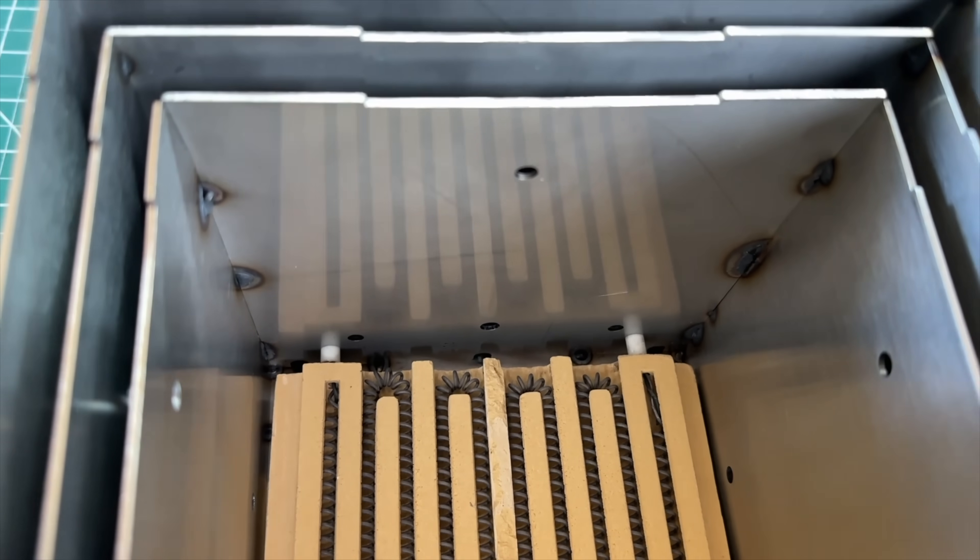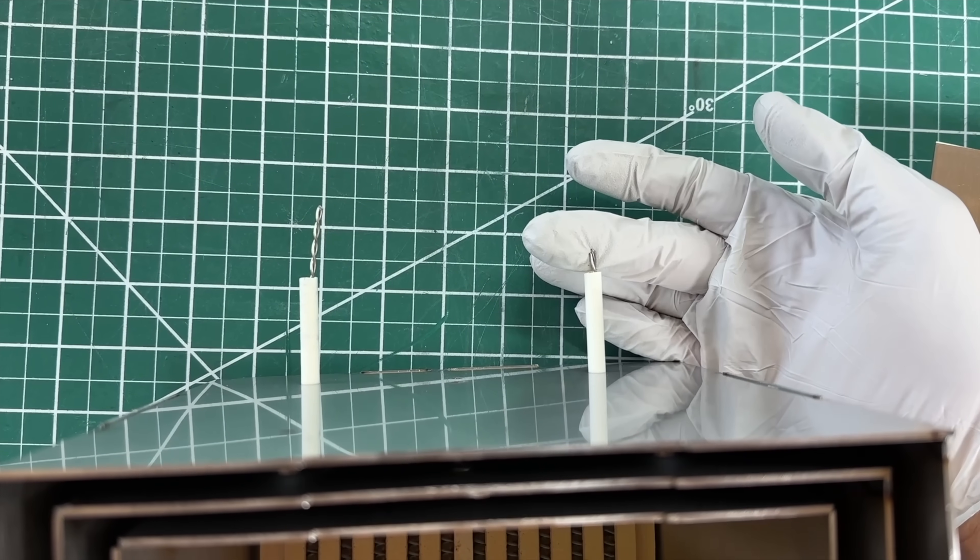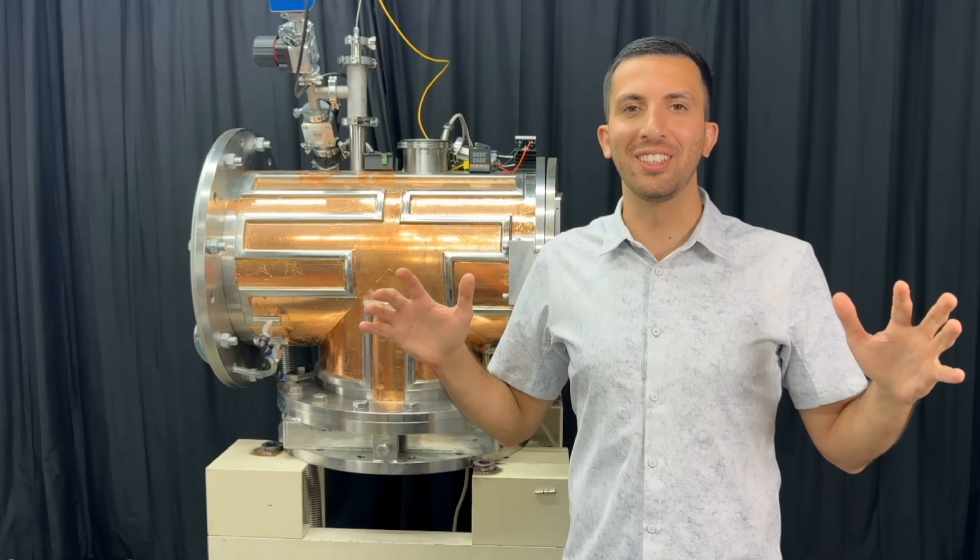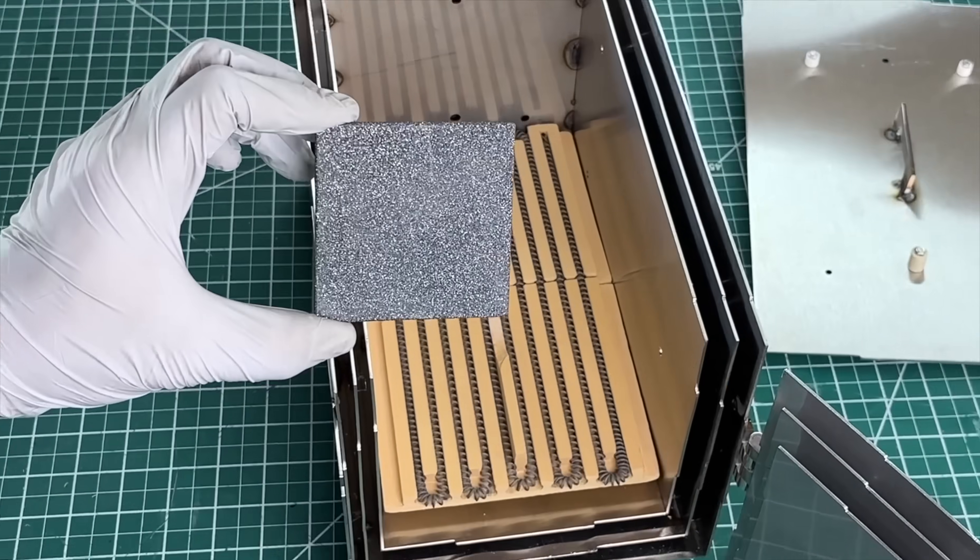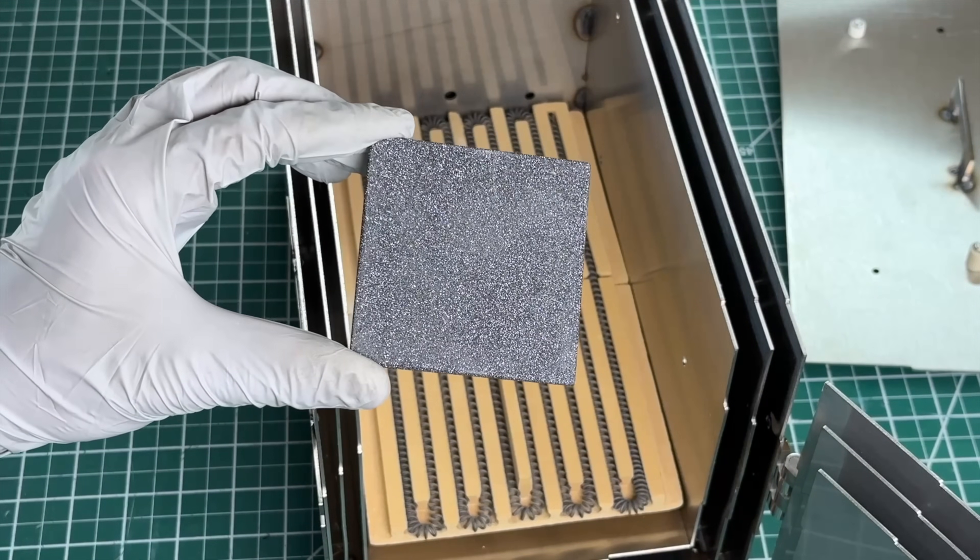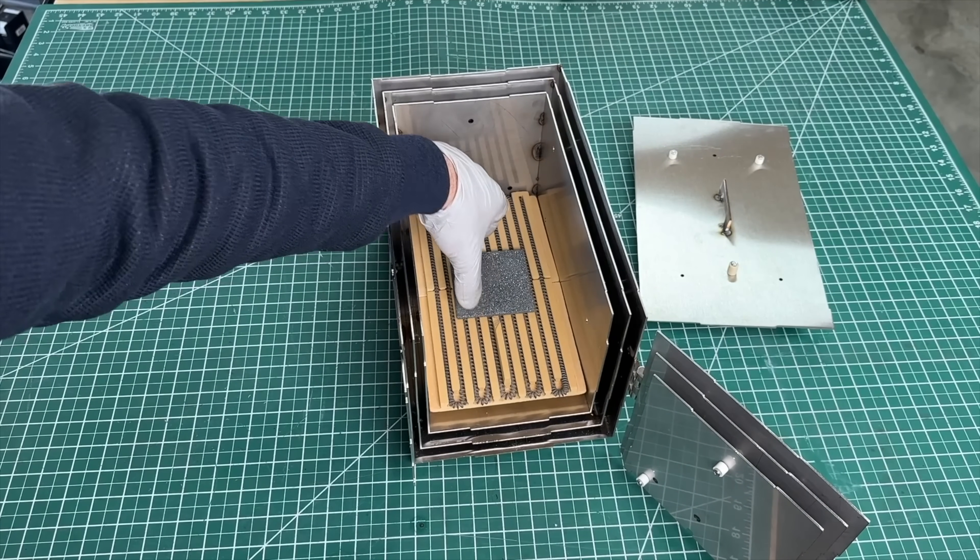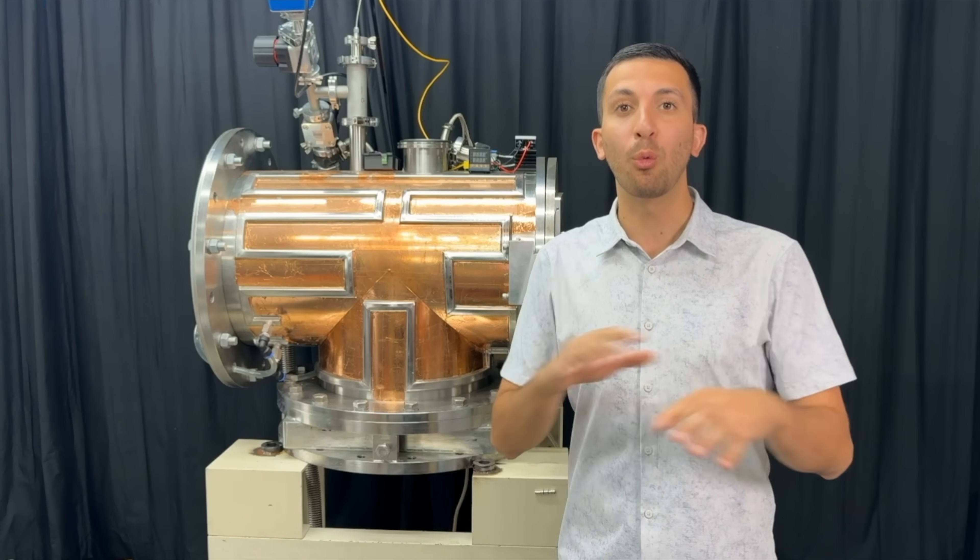Now the wires are insulated going outside where we connect the 110 volt power. Now radiation heats things up way slower than conduction. So to speed our process up, I decided to buy a silicon carbide square because it absorbs infrared radiation really effectively and it's also very thermally conductive, so it will transfer the heat to our sample really fast.